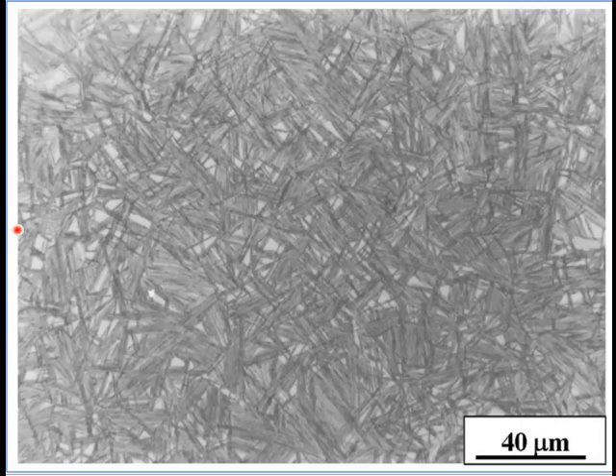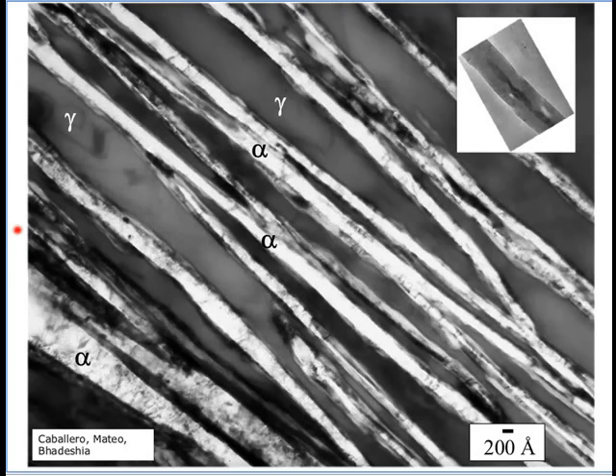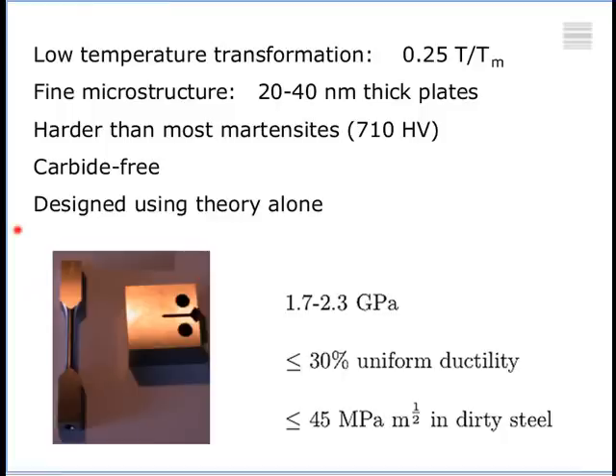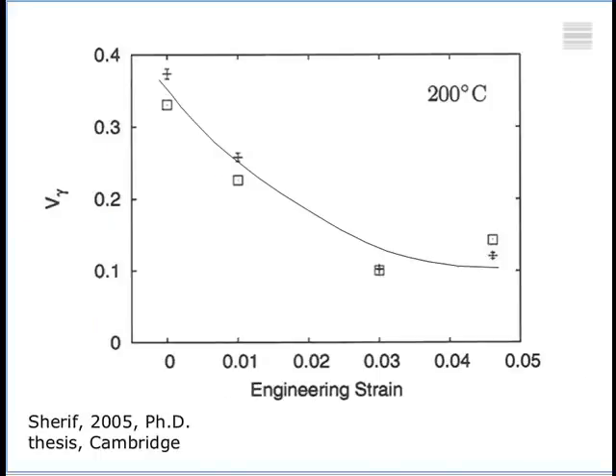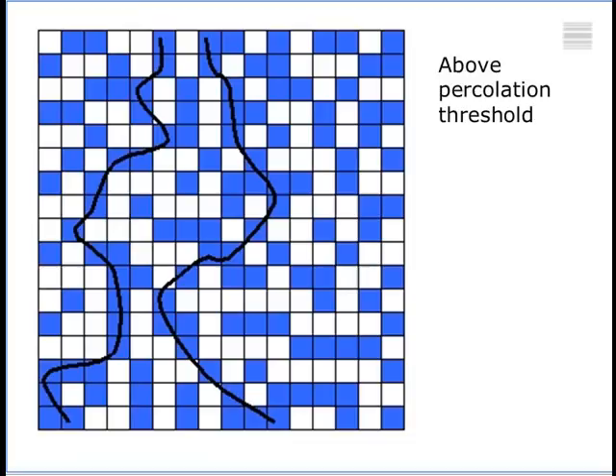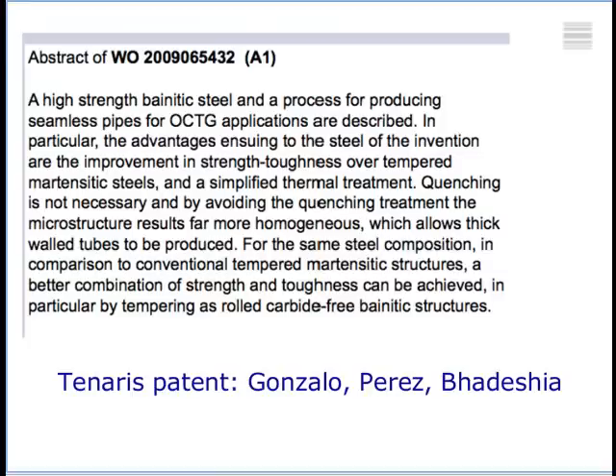That means a mixture of bainitic ferrite and austenite, but with one difference, is that we don't need this level of strength. This is something like 2.5 gigapascals in strength. We need a lower value of strength, about 1600 megapascals, and we need a greater toughness than 45 megapascal root meters. So how did we do this? Well, we first need to understand what controls toughness, okay? Because the Charpy requirements for such pipes are very severe. And of course, then you have to also be able to tolerate hydrogen and hydrogen sulfide and all the horrible things that happen down in an oil well.